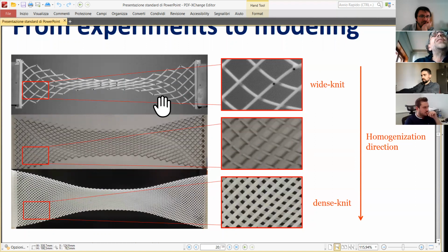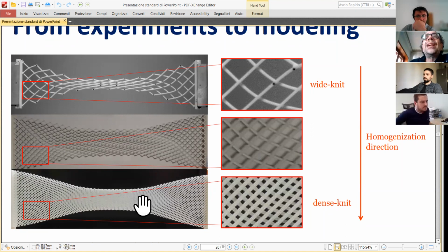All these three structures behave governed by the pivots properties and the bending stiffness of involved beams. However, here you have a very nice phase transition. When beams touch one with the other, then in the center of this material, you get a standard three-dimensional continuum, exactly as those which we are studying and teaching for our students. So you have a kind of second gradient material, which after a big elongation becomes a first gradient material.